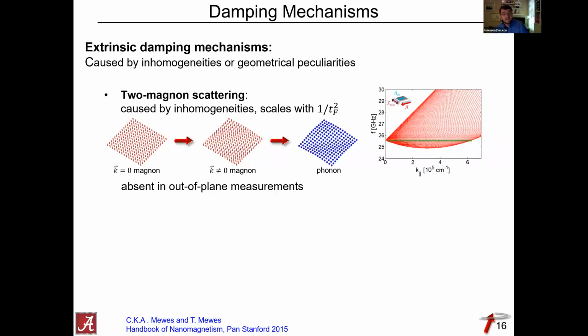To understand how this works, what is shown here is the dispersion relation of the magnons for an in-plane configuration, where the external field is applied in the plane of the film. At K = 0, that's the ferromagnetic resonance, and there are a whole bunch of propagating spin waves that are degenerate with the ferromagnetic resonance. So the K = 0 magnon can scatter into all these different magnons and thereby contribute to the damping. Another interesting part of two-magnon scattering is that it's absent in out-of-plane measurements, simply because there are no degenerate states into which you can scatter.